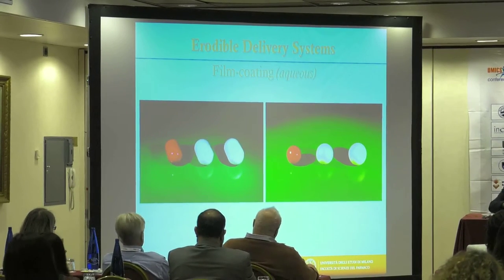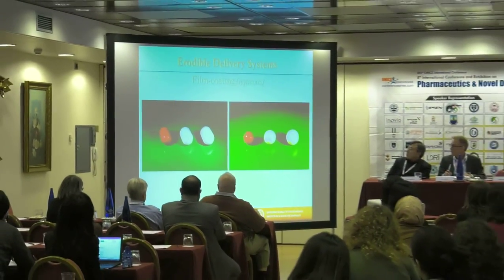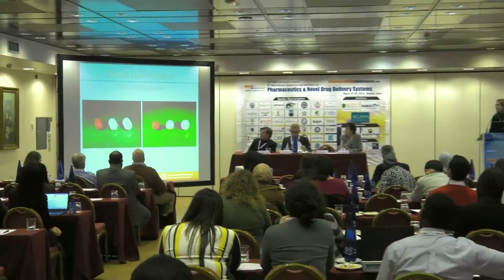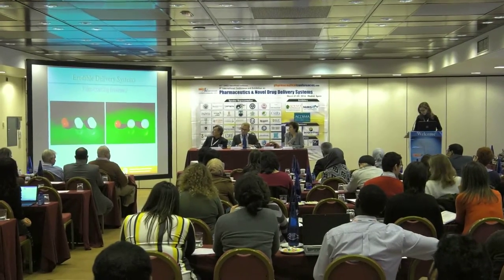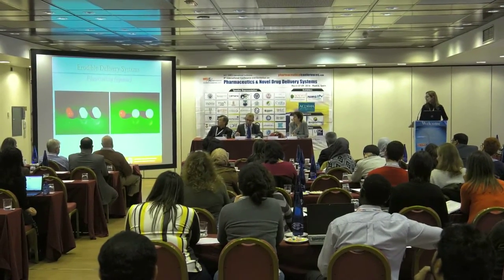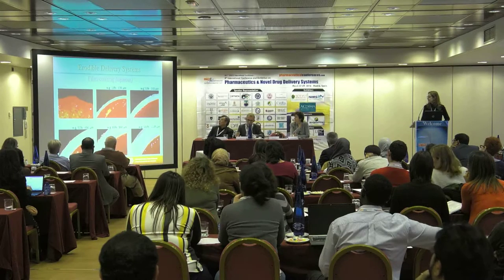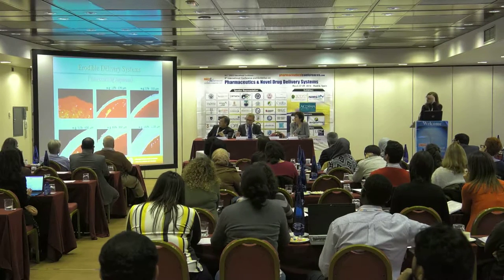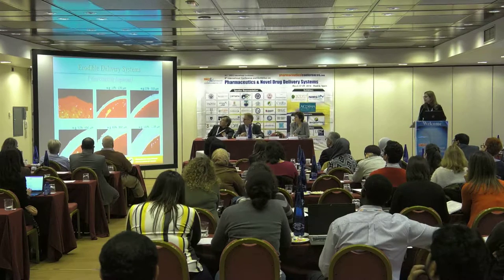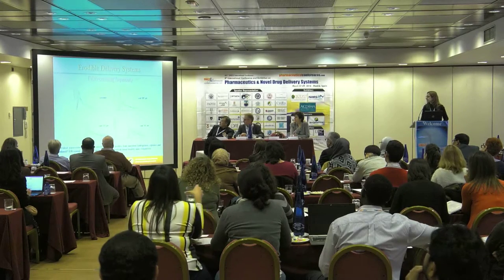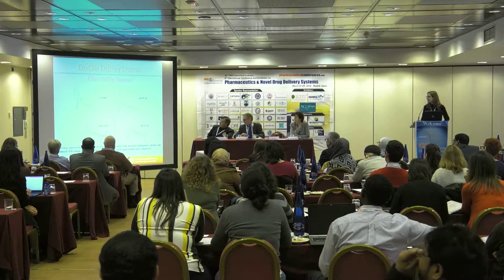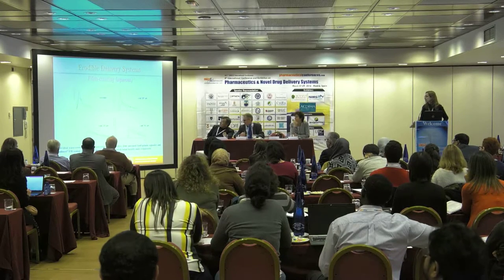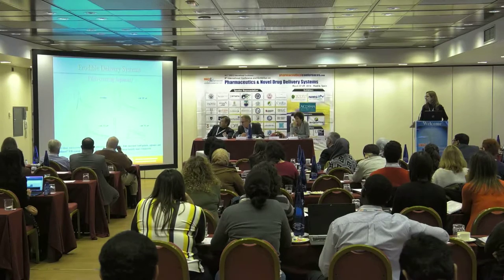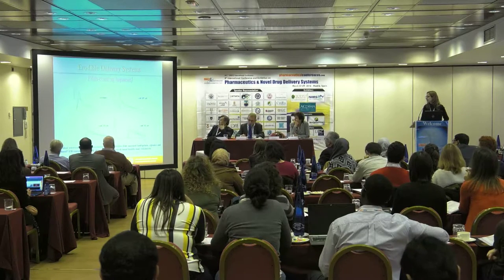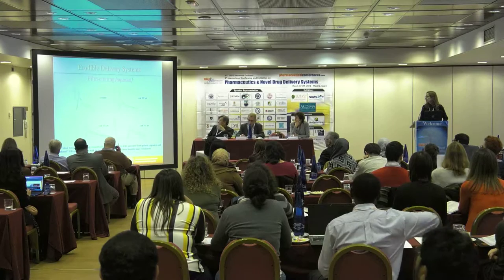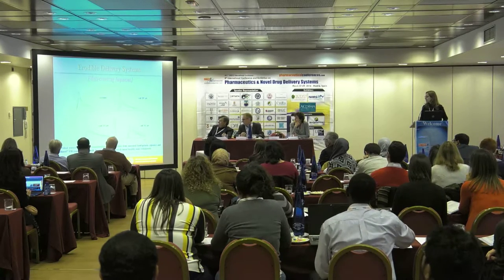As a result, the manufacturing of coated capsules, soft and hard gelatin ones, was possible with no need for a protective subcoating or a sealing subcoating. And weight gain in a fairly broad range were obtained. From coated hard gelatin capsules, a time-controlled release performance was obtained not only in vitro but also in vivo, with lag times increasing as a function of the coat thickness.